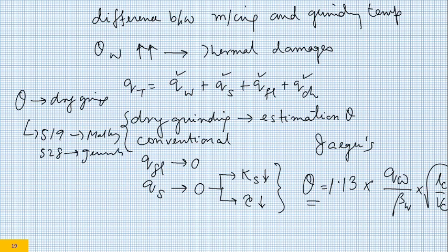Initially, during 7.1a, we talked about how the grinding temperature can be very high. Yes, it can be very high, but the numerical example that we have taken is not so high, but this is also high enough. 527, it would definitely introduce some kind of annealing, so you would have microstructural change, micro hardness change. It would also induce tensile residual stress. So this is a very standard representative value of temperature.